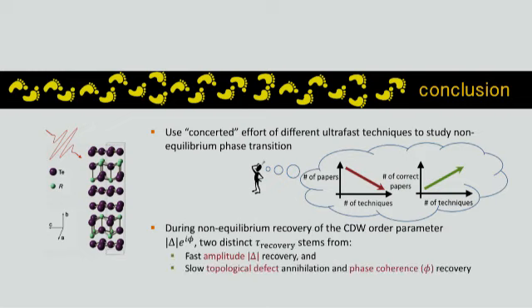The real conclusion here is that in this particular system, of charge density wave suppression and recovery, we see distinct time scales: the amplitude recovery is distinct from the recovery of the topological defects and the phase coherence in this material. And one message here is that a different time scale seen in different techniques is not necessarily due to decoupling of the subsystems, in this case electrons and phonons, in this kind of correlated material system.